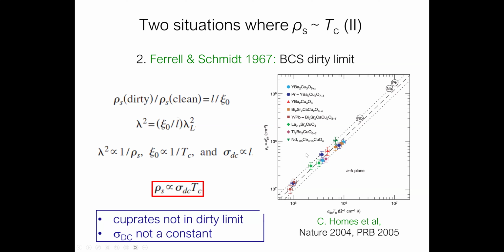including by Chris Homes in this plot where he plotted the superfluid density versus sigma dc times Tc and found for cuprates initially, and later for a lot of other superconductors, including S-wave superconductors, that they all fell on a line. This is a log-log scale, so be careful. But nevertheless, there's a kind of a remarkable scaling over several decades, which I will come back to at the end of the talk. The problem with this argument applied to the cuprates is that they're not in the dirty limit, and of course, sigma dc is not really a constant.